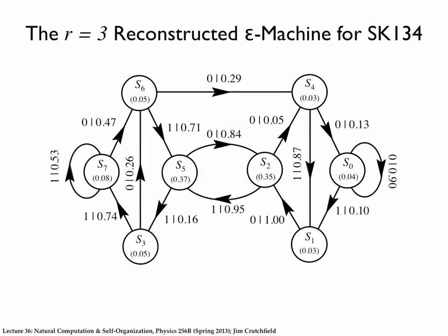Previous descriptions of the fault model, where people would use it, and describe this, we'll talk about in just a second, do not make a distinction between whether a slide occurs at this causal state initiating an extra zero, or whether a slide occurs at this causal state initiating an extra one. Our formalism can pick that up. Effortlessly. We didn't do anything to make it happen. It just did. And so if there is this type of asymmetry in the spectrum where you might think there should be some symmetry, we can find it.